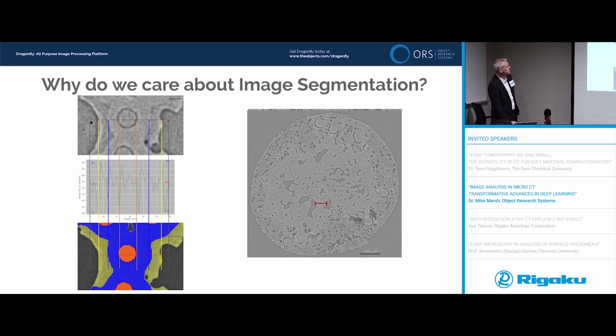And here we can look at it even further. As you probe the intensity as you move across this sample, the intensity of all of these materials averages between 148 counts and 152 counts. The scale is arbitrary here. But you can see that it's not like one material is high intensity and another material is low intensity. They're all about the same intensity. So segmentation is very demanding. And the area we're looking at right here is just a zoom in of this area right here.